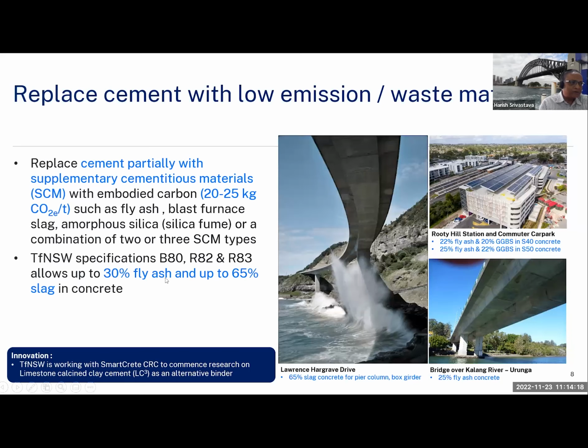In the transport specifications, I have cited some numbers, allowing up to 30% replacement by fly ash and about 65% use of slag. And at the moment, we are also working with the SmartCrete CRC on developing LC3, which will be an alternative binder. The pictures on the right are a real-time example where transport actually used fly ash and slag as a binary or ternary blend.